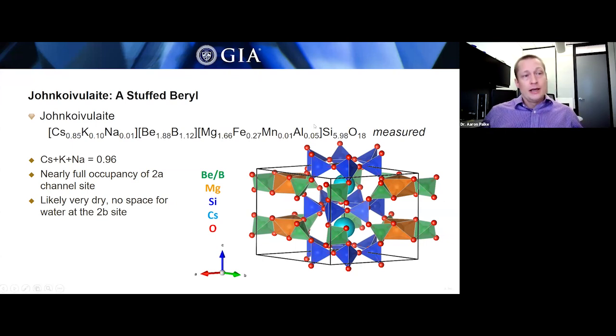And what happens in beryl, since if you have very little occupancy of that site, nature doesn't like a vacuum, right? So something typically tends to go into those channel sites because this is a big empty space in the structure. Typically with beryl group minerals, you stuff a lot of water into those channels in between those silica rings. In the case of johnkoivulaite, this site has almost 96% occupancy. That means that compared to other beryls, johnkoivulaite is a very dry beryl group mineral. There's not very much water because you can't stuff much water when those sites are filled with all that cesium. So we can call johnkoivulaite a stuffed beryl group mineral.